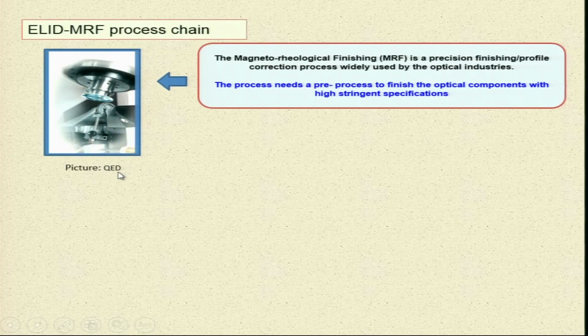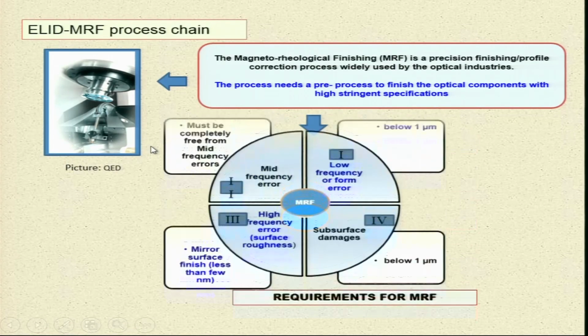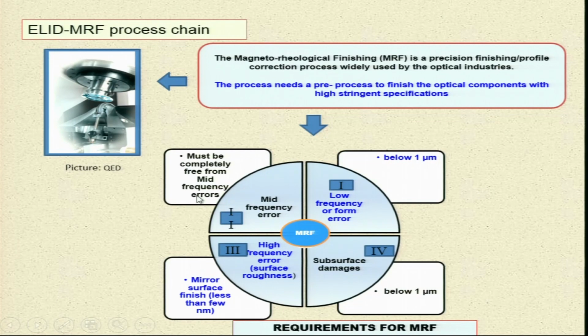That you can see over here. This is a picture of the QED machine. This is the wheel and this is the component to be finished. You can see here it must be completely free from mid frequency error. This is the low frequency or form error, where you can have less than 1 micrometer. Mid frequency error must be completely eliminated by conducting MRF. High frequency error, surface roughness, mirror surface finish less than a few nanometers, as I have mentioned to you, and subsurface damages that may be below 1 micron. So, these are the requirements for the MRF process.